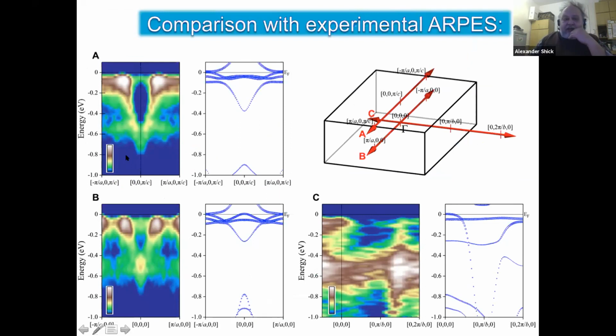Here are the Fujimori results, here, here, here, and here are our calculations. You see that near the Fermi edge, the bands really fit very well to what they measure. Here, here, and here.